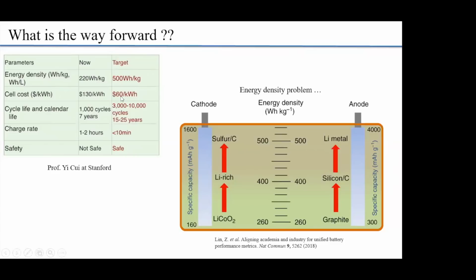I mean, even if you get to $100 per kilowatt hour, and if you can push it to 400, that's a big achievement in itself, and maintaining cycle life and then charge rate. So do we need to get to 500 watt hours per kilogram? It seems like 400 is pretty great. I suppose if the energy density is higher, then there are more applications. But right now, Tesla's got a 370 mile Model S. You're starting to get pretty close to parity with internal combustion engine ranges.